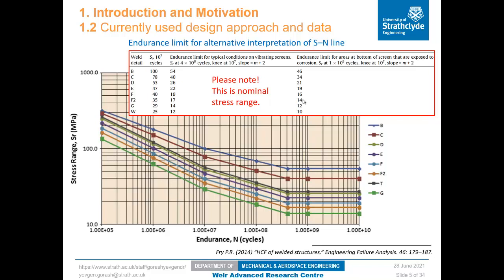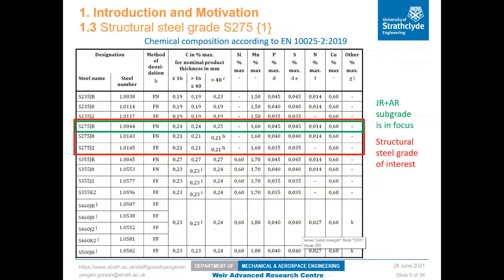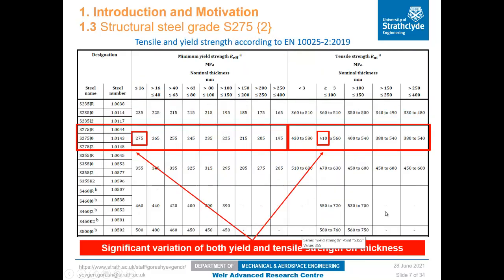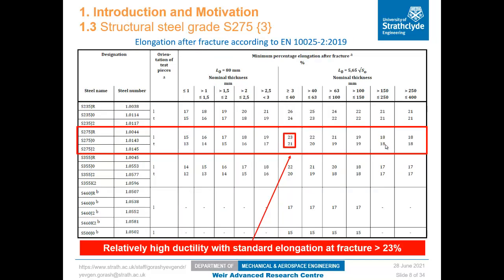And this fact motivates our research to look at the particular grades, subgrades, in the gigacycle domain and investigate the real fatigue performance. In the focus of our research is grade 275JR as rolled, according to the European standard EN 10025-2. When looking at its mechanical properties, we can see that there is a variation of yield and tensile strength, and typically what we should expect is 275 megapascals of yield strength and 400 megapascals of tensile strength. When looking at the ductility, its minimum requirement is 23%, but in reality it's a bit higher.